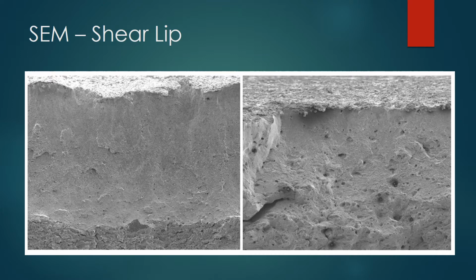So, as Gabe was talking about, you can see on the additive manufactured sample, which is on the right, that we don't have a very distinct shear lip. On the left, you see a very distinct shear lip on the machine sample right at the bottom of the image. Whereas on the right, it looks very muddled and you can't really tell what exactly is happening. You're also already beginning to see evidence of severe porosity in the additive manufactured sample.